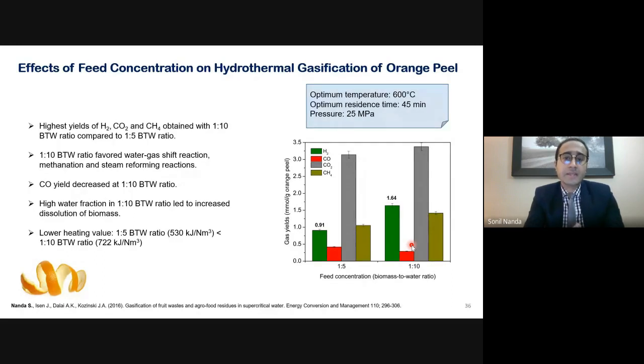These free radicals and ionic products of water, which were generated in a higher magnitude at higher water concentration in the 1:10 ratio, resulted in easy solubilization of the material, of the food waste or any complex material, to produce more hydrogen gas. And moreover, since there is more water content in this 1:10 ratio, some of the hydrogen also came from the water as a result of the splitting of the water at high temperature in supercritical condition. Therefore, the 1:10 ratio was optimal for high hydrogen yield.